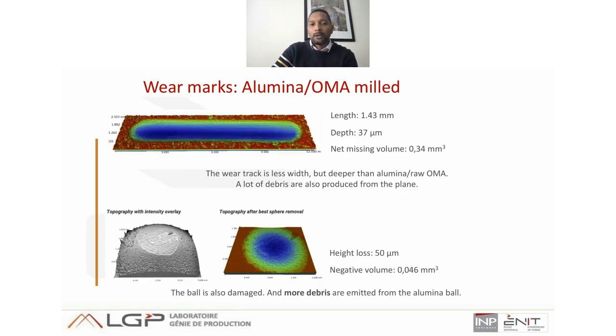When we use milled OMA, we use microballs to resurface the coating. We have new lengths and new depths that are approximately the same as with the raw material. The wear track is a little less wide, but quite a bit deeper than with raw alumina. There is a lot of production of debris also, and we see damage on the ball with scratches, and a few more debris are emitted from the alumina ball.